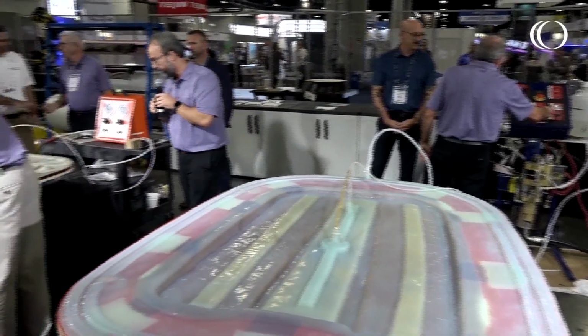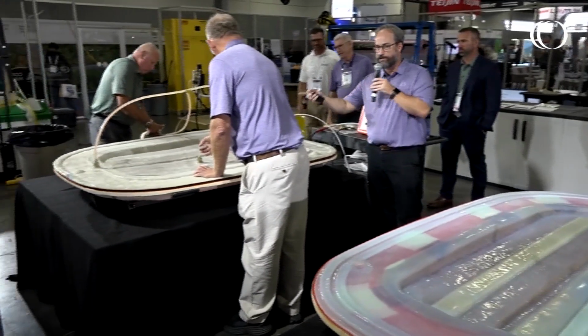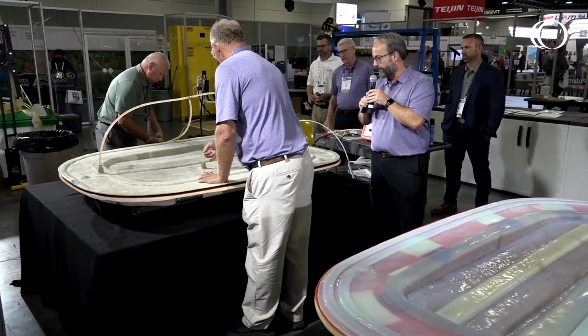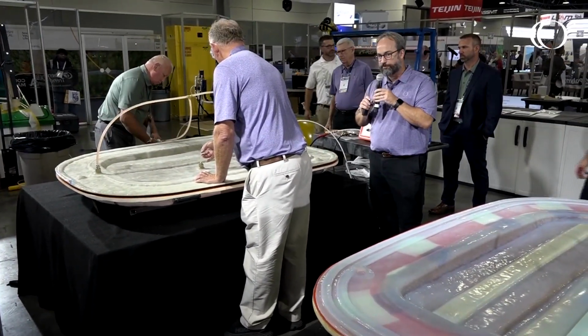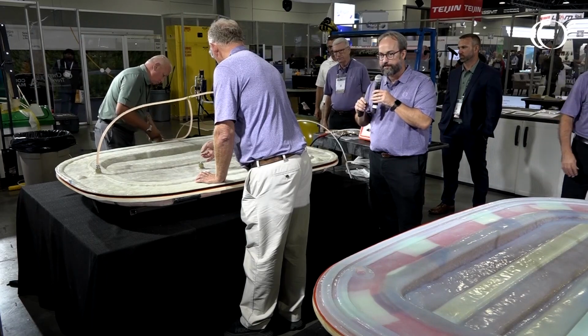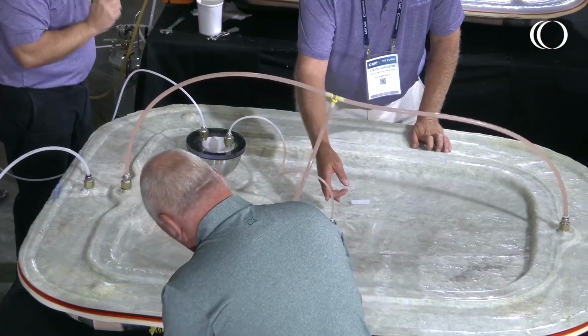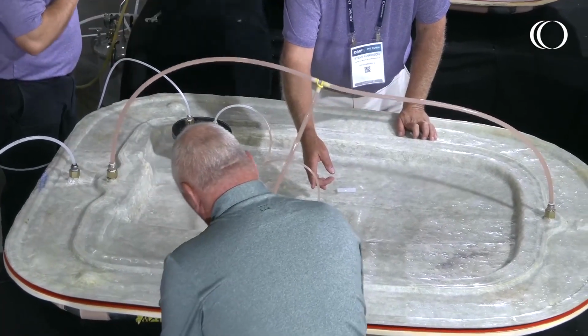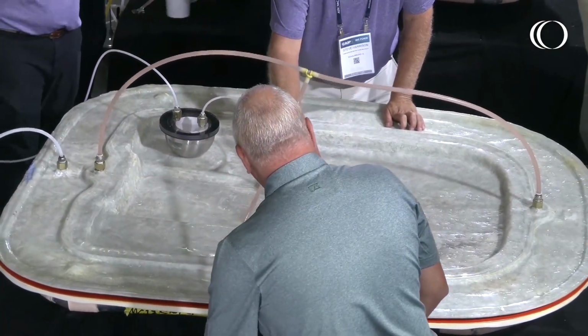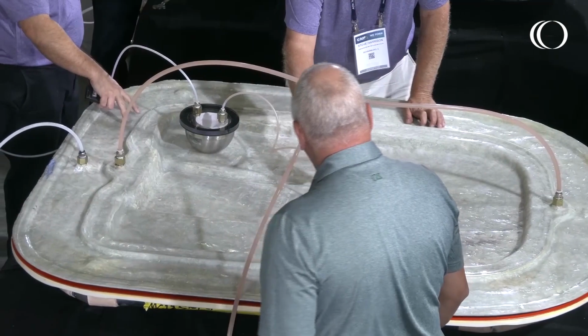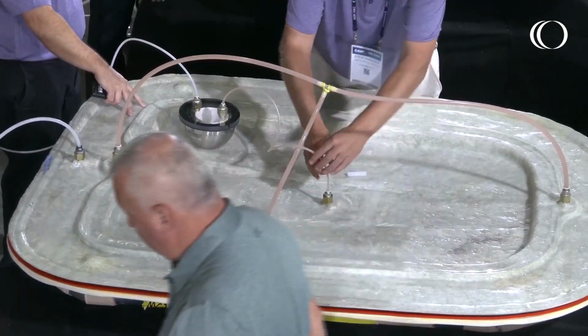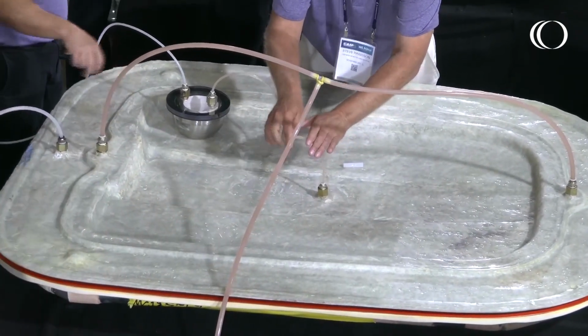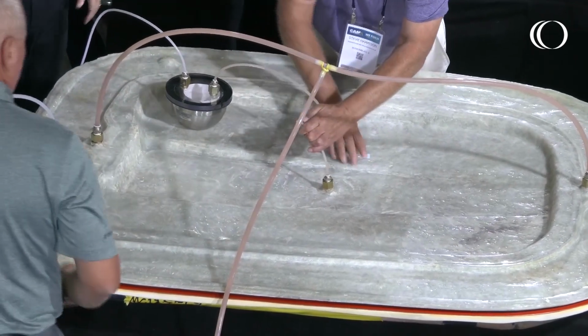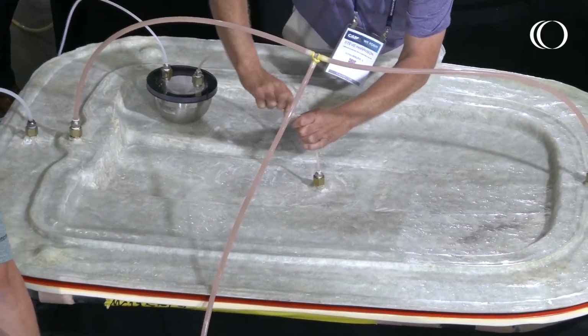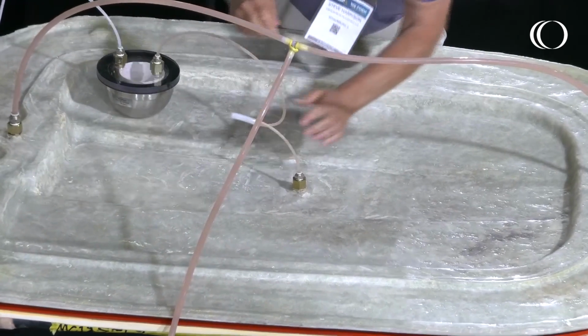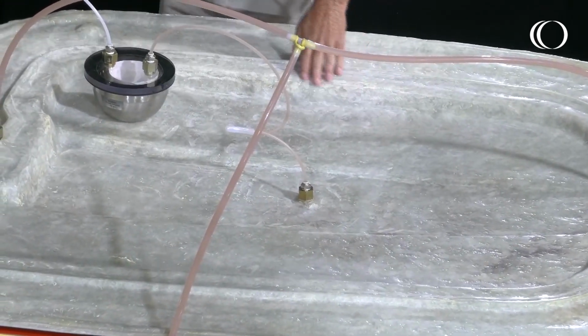So over here on the Light RTM, you can see the resin coming out of our vacuum vent. We have a few bubbles. So we'll wait till that runs clear and then clamp that off. And then our part is full. Our full vacuum on our clamping flange will keep the mold closed until the part cures. So Steve's clamped the vacuum vent on it now, and the part is full. Now we just wait for the resin to gel and cure.